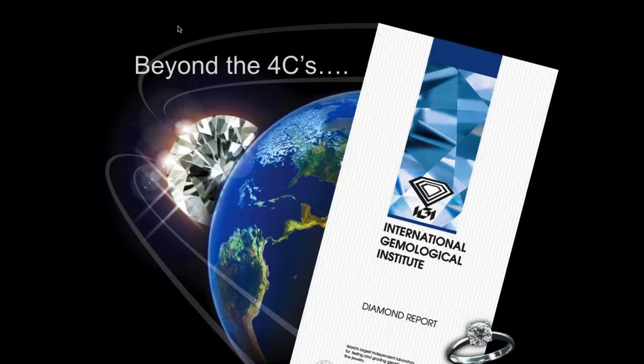Are there chances of color changing in goods which have been treated? Yes — with current treatments like HPHT, there are absolutely no chances of the color being reversed, so it remains the same. However, if it's heat treated or other very low radiation treatment, there could be a possibility the color could change. It depends on the type of treatment that has been done on the stone.